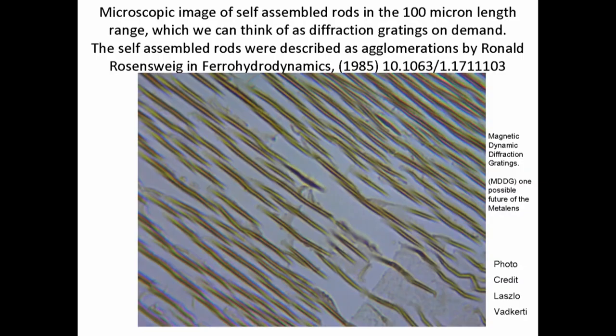And you might wonder, how is this possible? This is probably the most important slide I have. Ferrofluid particles are designed to repel other ferrofluid particles unless you apply an applied field which overcomes that repulsion and the particles start sticking together. These particles are in a field gradient, so they're moving at the same time that the rods are growing. What's really happening here is we're self-assembling a diffraction grating. When you remove the field, these chains dissipate. So when you apply the field, you get a diffraction grating, and when you remove the field, you lose the diffraction grating.